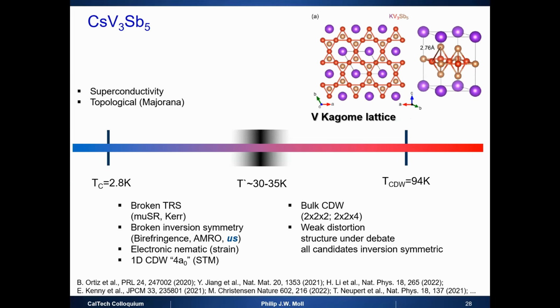There's a lot of things about interacting phases I don't have the time to go into. We can discuss. But what is very clear here from uniaxial strain measurements or pressure measurements is that there's a strong antagonistic role between the charge density wave and the superconductivity. So if you somehow suppress the charge density wave temperature, your TC goes up and vice versa. So clearly these two compete for density of states. At least that's the general law. And so now you could imagine, what if you stabilize a system where you could somehow on a chip level change the charge density wave transition? Can you then somehow switch superconducting TC?